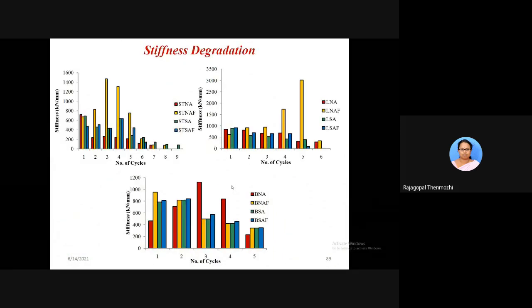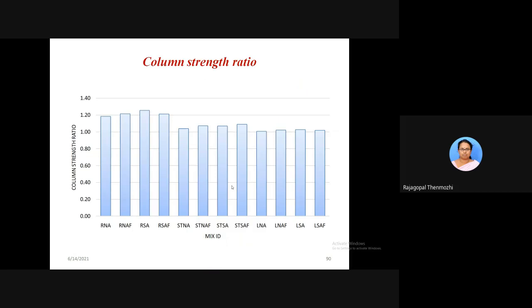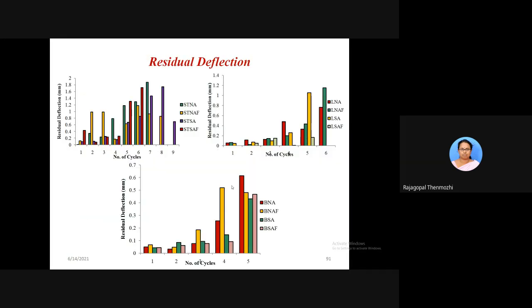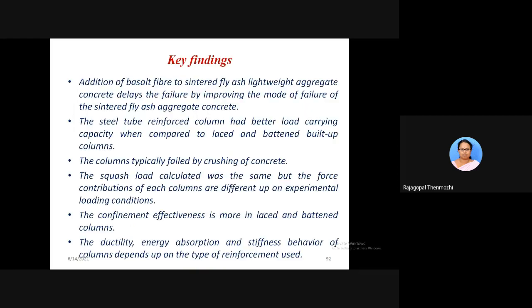So these are the stiffness degradation curves. For each and every column, this picture shows you the column strength ratio. Though it is made using sintered fly ash aggregate, we were able to get the values of maximum strength. So these are the residual deflections.